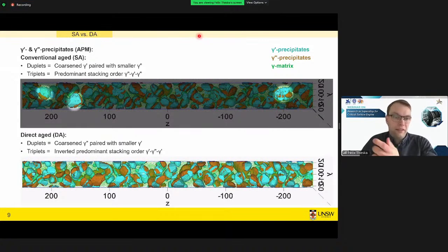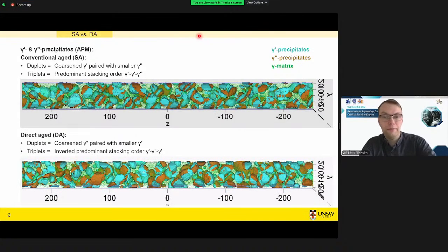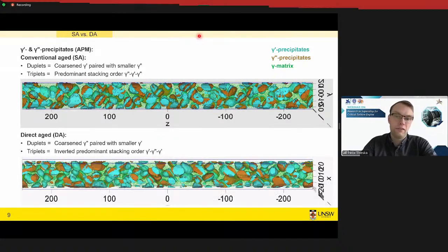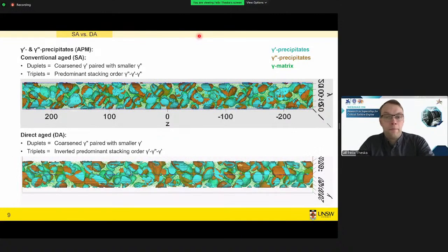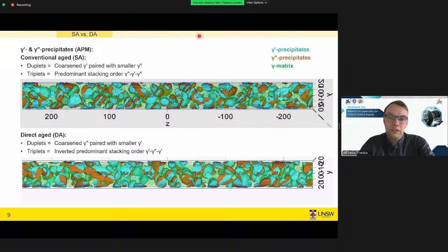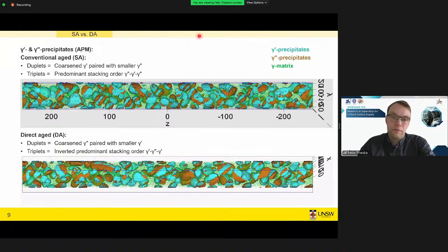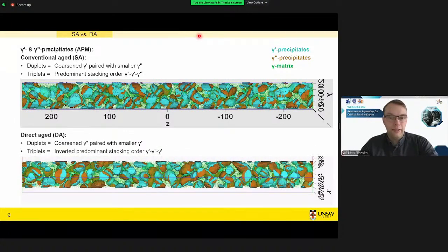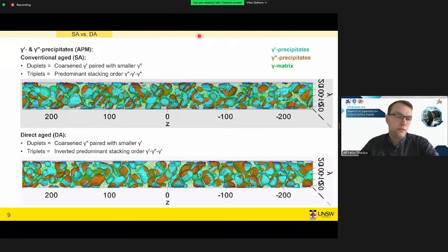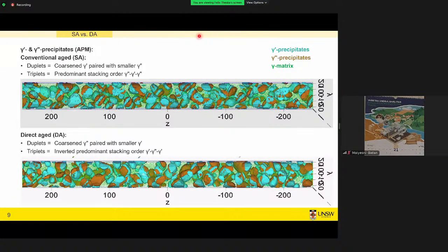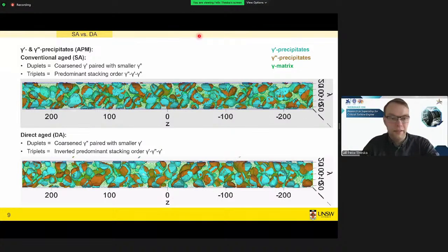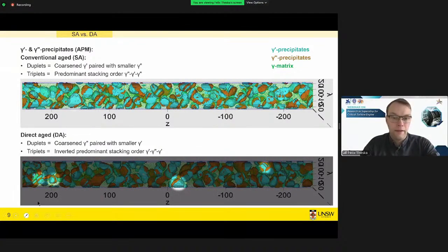On the first side, the direct age material looks very similar. Again, we find these particles sitting together. But if we look closer in more detail, we find that now gamma double prime likes to sit in the center or to form the larger part of these particles. The highlights should pop up. Yeah, as you can see here, these triplets, and here the duplets.